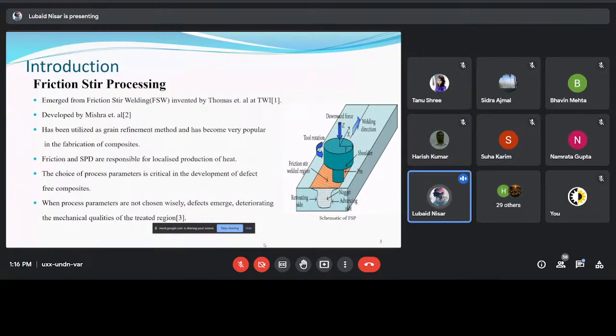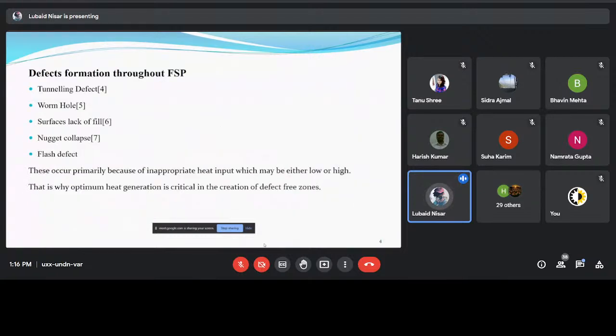This process is actually based on certain process parameters, which include the rotational speed of the pin, the traverse speed, the plunge depth, the tilt angle, etc., which if not chosen correctly, will result in the formation of defects. These defects further deteriorate the mechanical properties of the processed zone. So some of the defects that we observe throughout the friction stir processing are as follows.